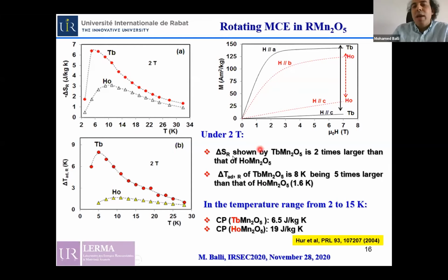As I explained before, the difference between the magnetocaloric properties of terbium and holmium compounds are mainly attributed to the difference in the magnetic behavior of their magnetic moments, in addition to the strong magnetic anisotropy shown by the terbium compound, as clearly seen in this figure.